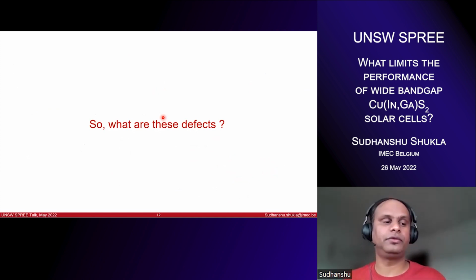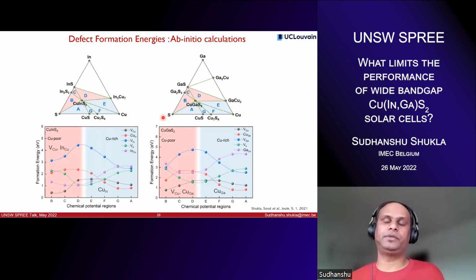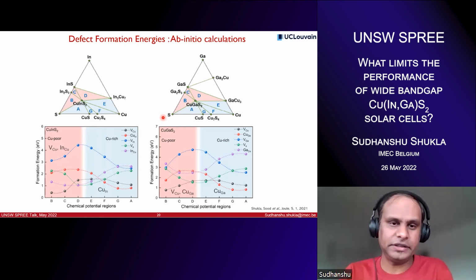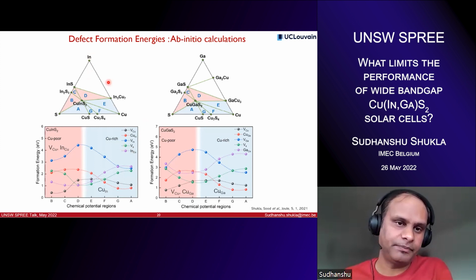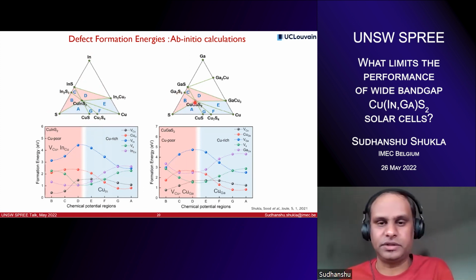So far we did not say anything about the nature of these defects. So we approached our theoretical colleagues and we tried to look at the formation energy of various defects. So this is the range or the regimes where the calculation was performed. The blue refers to the copper-rich domain and the pink one refers to the copper-poor domain. This is for CIS, and then the right one is for the CGS.